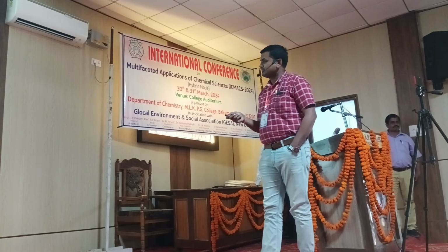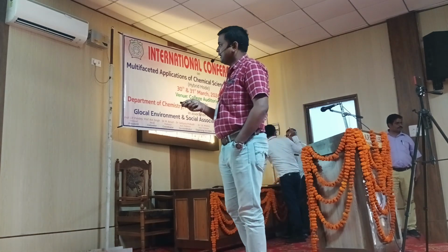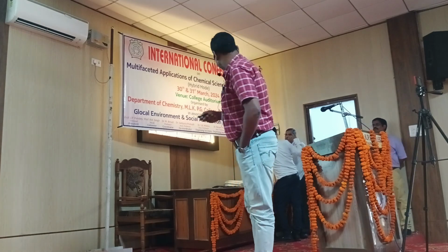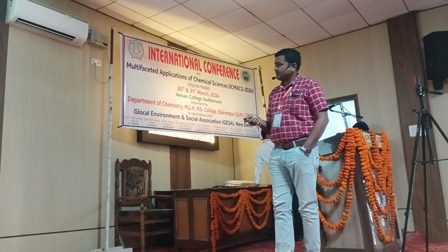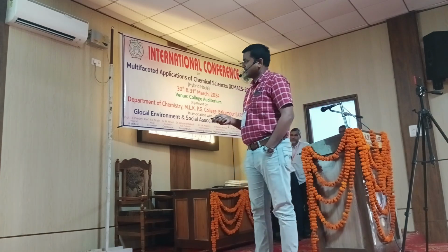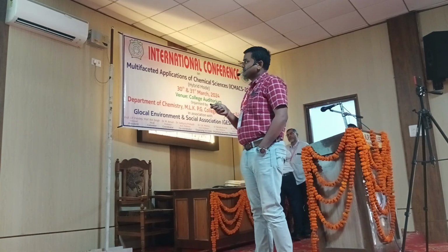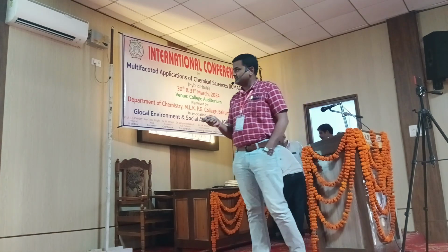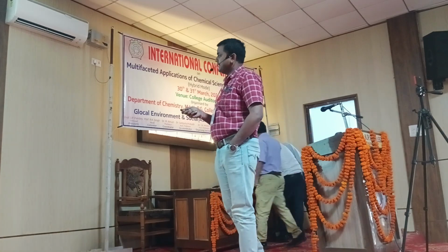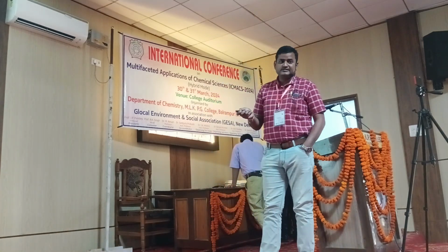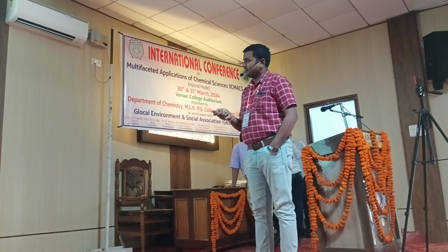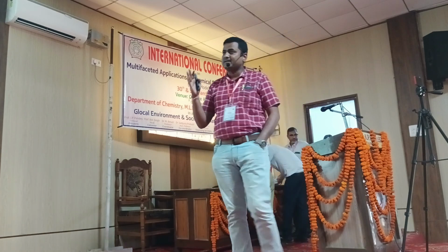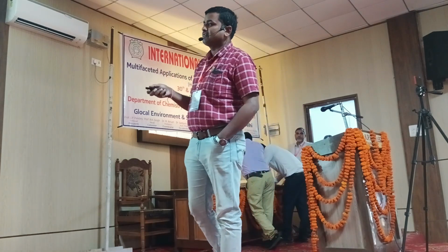This is the visible light. In the normal light, we obtained the yellow color of graphene quantum dots. We have not only focused on ethylene diamine; we have explored this graphene quantum dot from coal soot in various solvents like H2O, ethanol, THF, DMF, DMSO, and ethylene diamine. But we did not see any white light emission in the case of H2O, ethanol, and THF, because in these solvents we are getting only the monomer emission, which is coming from the blue region.